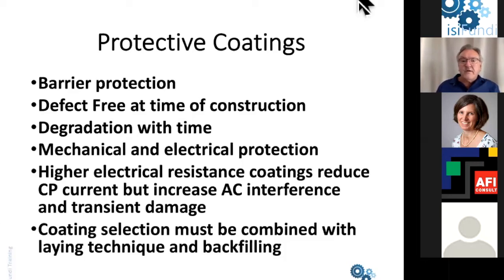And this is one of the interesting developments that's come up over the years. As we get better and better coatings, we get better and easier cathodic protection, less cathodic protection current, but we are finding that we get more and more AC interference as the coating insulation values increase. We also need to be careful that the coating selection is combined with the correct laying techniques and backfilling in order to prevent significant damage to the pipelines during construction.